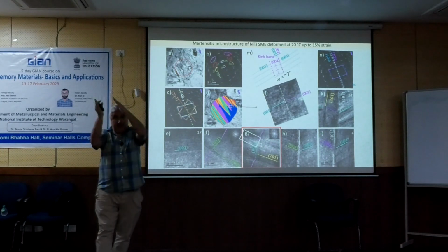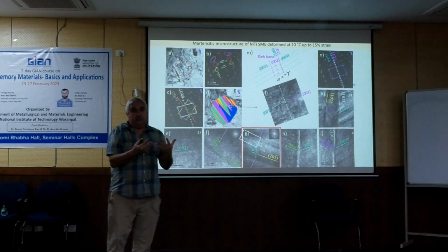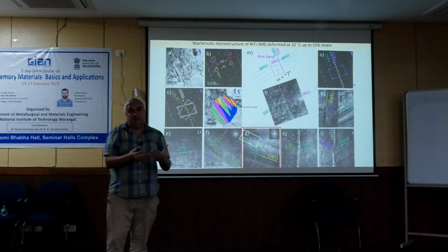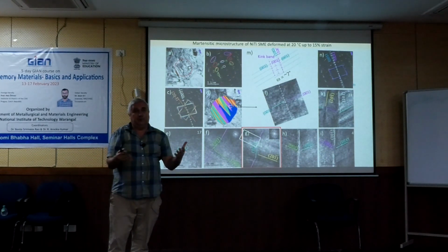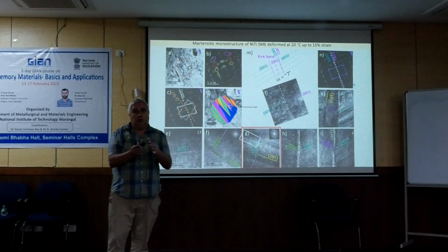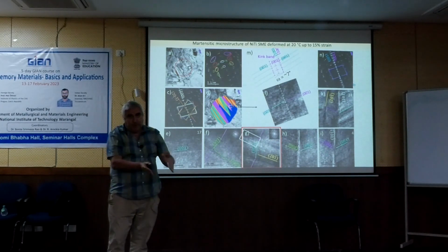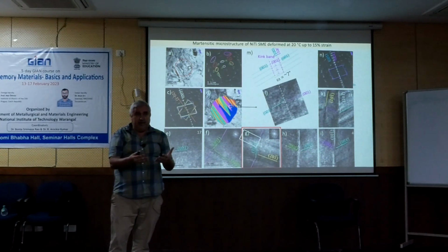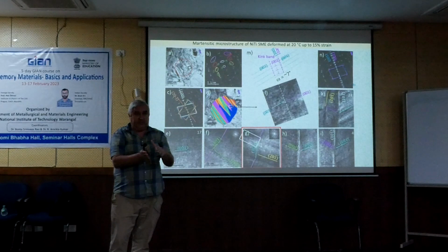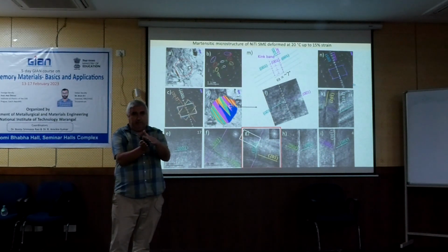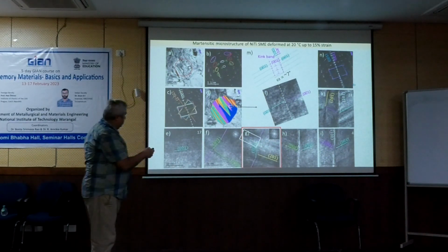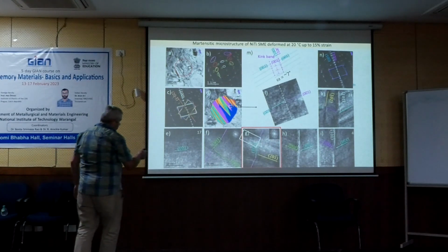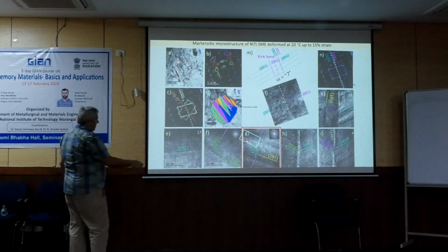You have matrix and a thin plate in between, which is a mechanical twin. Many materials deform by mechanical twinning, magnesium, titanium. So this is always two parallel interfaces. So when we speak about kink bands or twin bands, we always have two parallel interfaces and a plate between them, just like it is shown here or here.